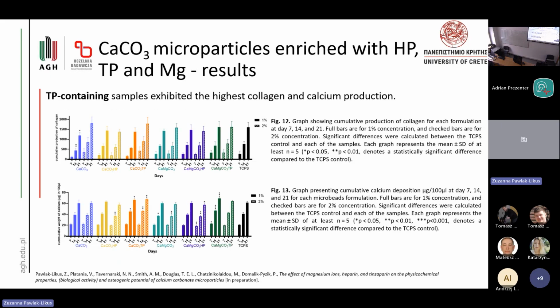Here are some other results of osteogenic assays. Above there is a collagen cumulative production assay, which quantifies the amount of collagen produced by cells over time, and it indicates extracellular matrix synthesis and osteoblast maturation. Below there is a calcium deposition assay that measures the accumulation of calcium salts deposited by cells, and it also indicates late stage osteogenic differentiation. From our results, we can see that here also TP containing samples exhibited the highest collagen and calcium production, which means they supported osteogenic activities the most.